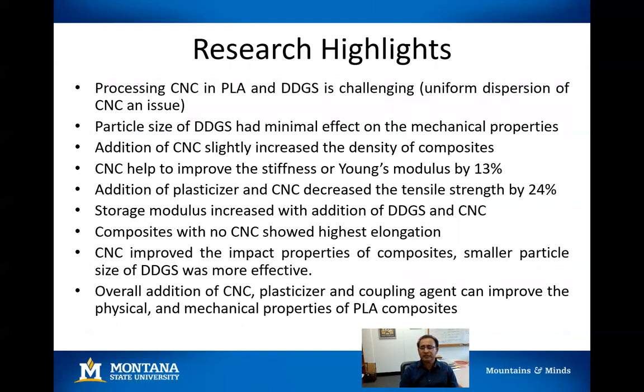So overall, from this research, we found that processing CNC in PLA and DDGS is challenging. The major issue is the uniform dispersion of the cellulose crystals in the PLA. The particle size of DDGS had very little effect on the mechanical properties of composites, and we found addition of CNC slightly increased the density of the composites, and also CNC improved the stiffness, Young's modulus, by around 13% in different formulations. We also found that the addition of plasticizer and CNC decreased the tensile strength by almost 24%.